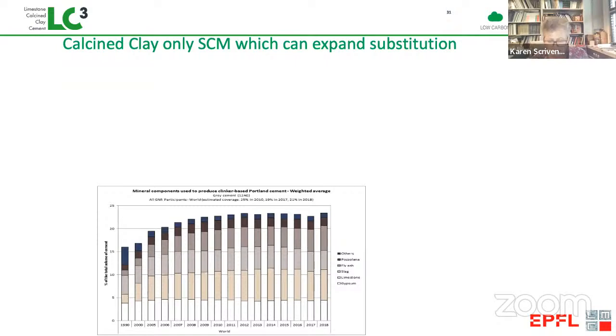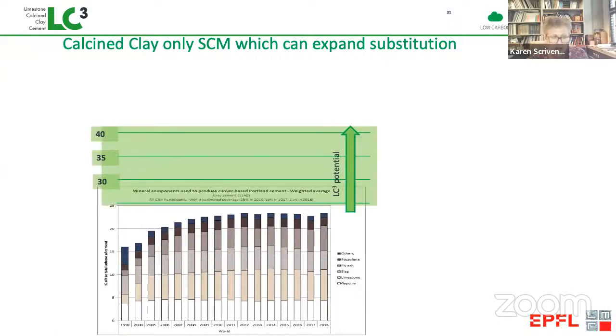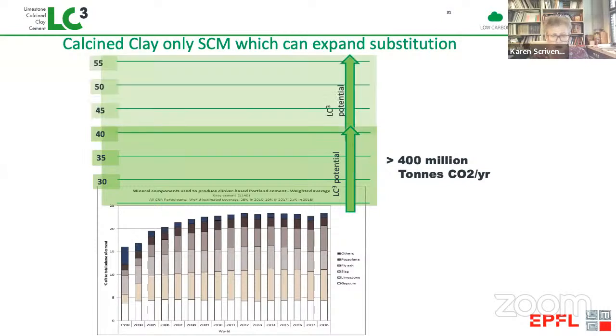If we remove this limitation, if we increase the supply of SCMs by having calcined clays, we can easily imagine going to a substitution level of about 40%, which would be equivalent to saving worldwide 400 million tons of CO2 per year. And I think on a horizon of something like 2050, we actually could go much further than this, to an average substitution level maybe up to 55%, which would be equivalent to 800 million tons of CO2.